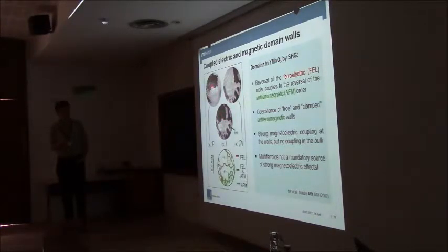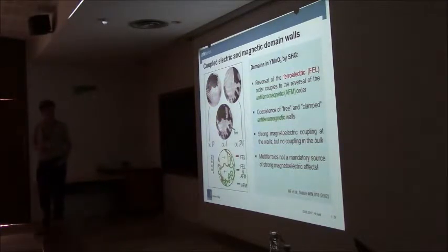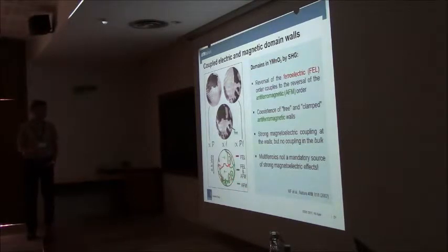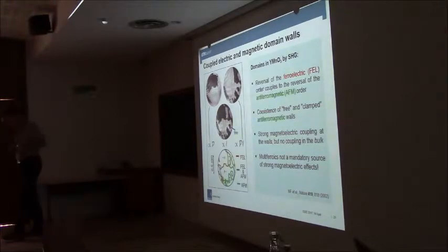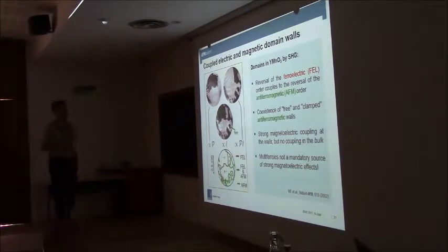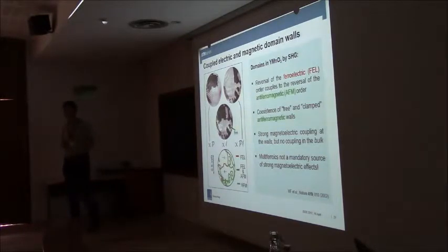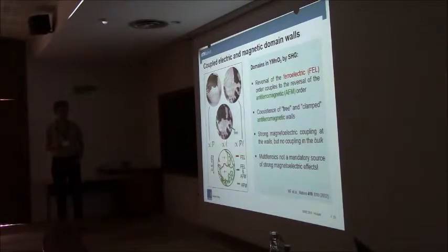So you have a ferroelectric domain wall, you have an antiferromagnetic domain wall wherever there is a ferroelectric domain wall. You have additional antiferromagnetic walls, but as I said, wherever there is a ferroelectric wall, you also have an antiferromagnetic wall. And this was then surprising, especially because this compound does not allow linear magnetoelectric coupling. So this coupling between magnetic and electric domains must come from the domain walls. So that's an early work where domain walls, multiferroic domain walls play some role.